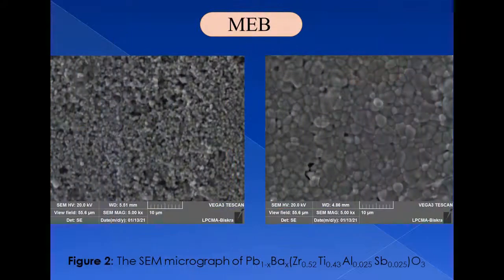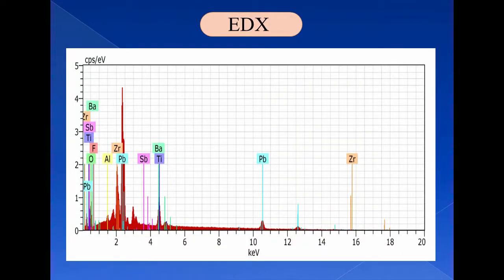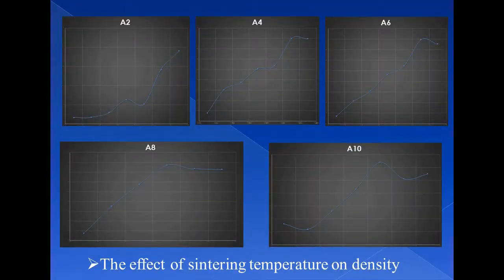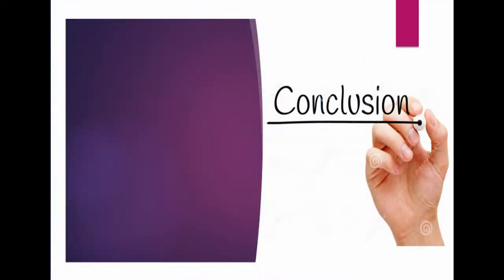The texture, porosity, and grain size of the sintered materials were observed by SEM. The chemical microanalysis was made by EDX. As we have seen, regarding the effect of sintering temperature on density, except for the curve A2, we have almost obtained curves that show that the optimal temperature at which we have obtained the maximal density is 1230 degrees Celsius.